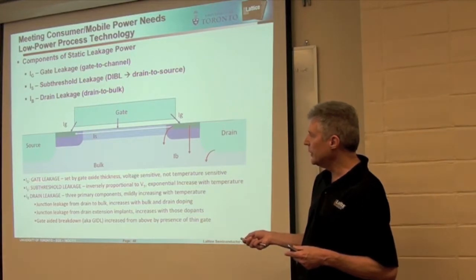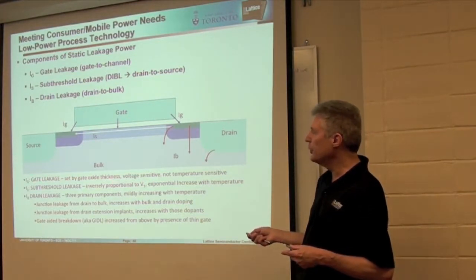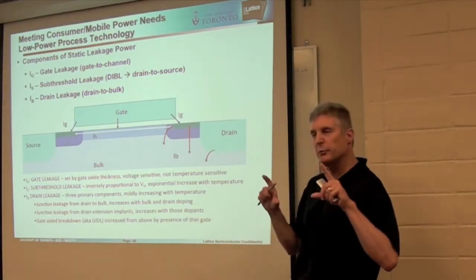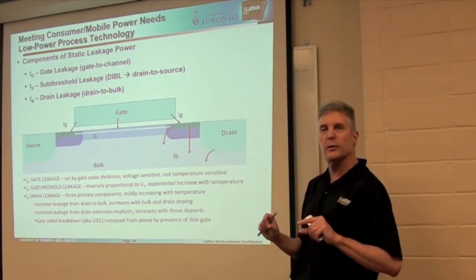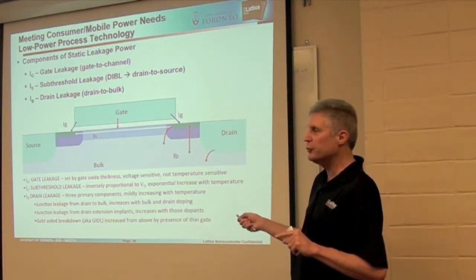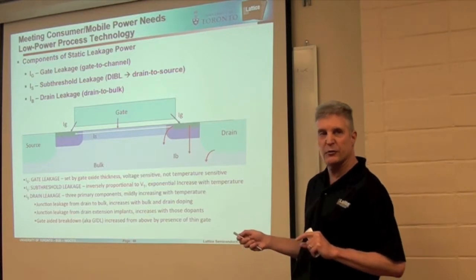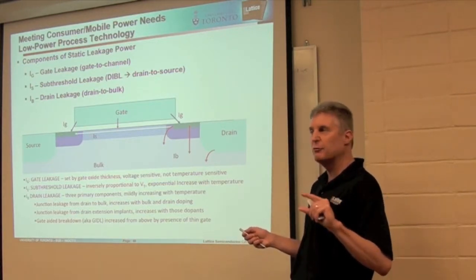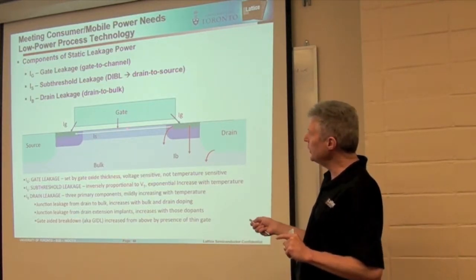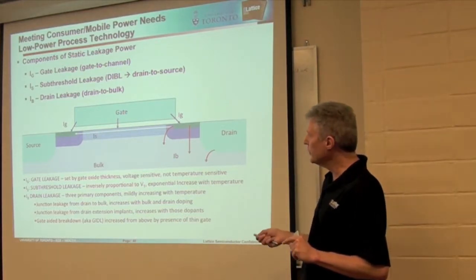And I just highlight here the gate leakage is controlled completely by the gate oxide thickness. The thicker it is, the less it is, the thinner it is, the more it is, and that's an exponential relationship as you get to thin oxides. So 1 or 2 angstroms can be a factor of 10x difference. So tuning that gate oxide is very important.